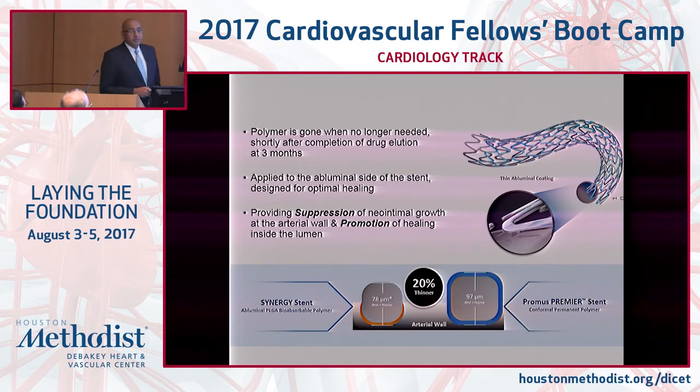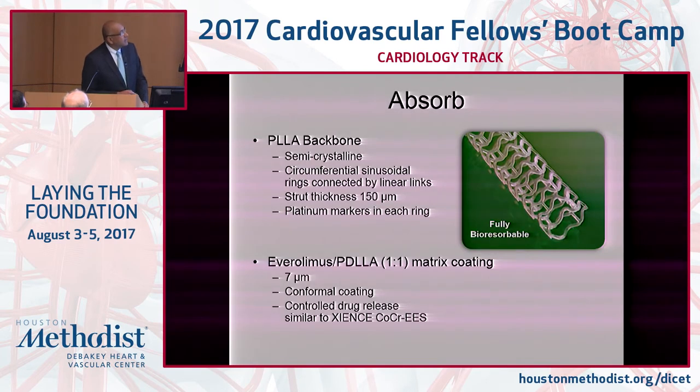We have a new type of stent which is approved, and a lot of the cath labs would have that. The idea behind this Synergy stent is to only give the drug on the arterial wall side, which is kind of very thoughtful, because if you think about it, the restenosis comes from the arterial wall side, not the luminal side. So why in the world do you want to put drug molecules there? And if you don't want to put drug molecules on the luminal side, we really don't need a polymer, because polymer may possibly crack, may actually cause chronic inflammation. So you put a polymer on the abluminal side, and then you only elute drug for 3 to 4 months, and that potentially may have benefit of that technology.